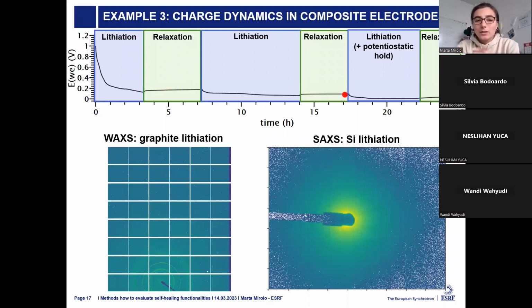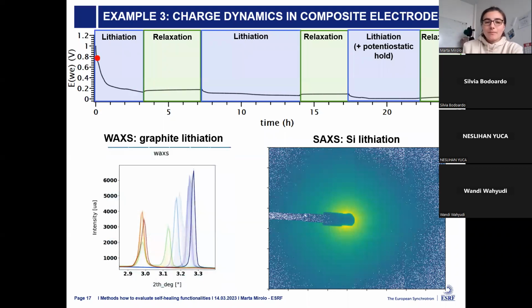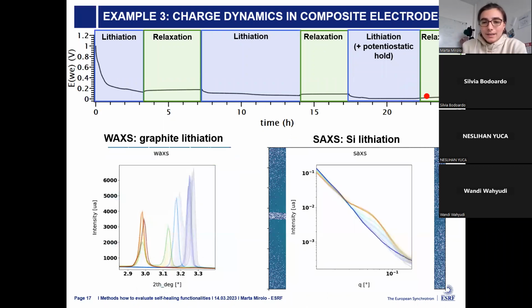Wide angle X-ray scattering is, let's say, what we know as X-ray diffraction. So we can study the lithiation of graphite via the peak position of the graphite. Graphite is a crystalline material, so it's very easy to investigate. And we can also look at the silicon lithiation by looking at the evolution of the small angle X-ray scattering